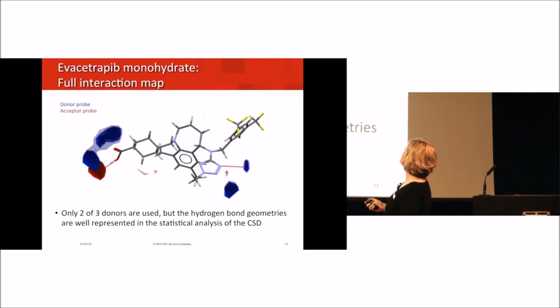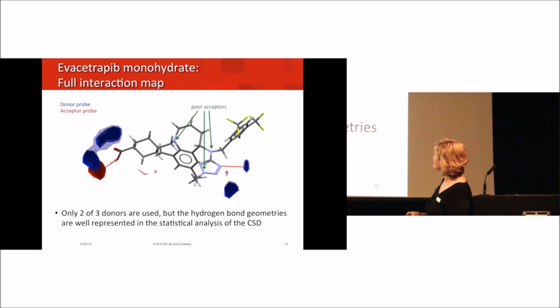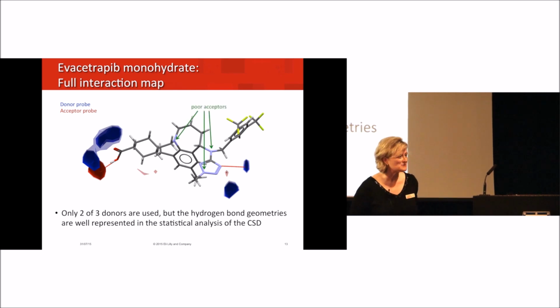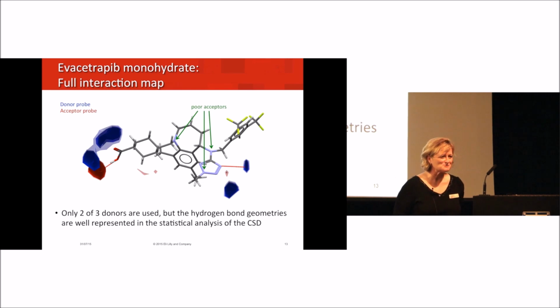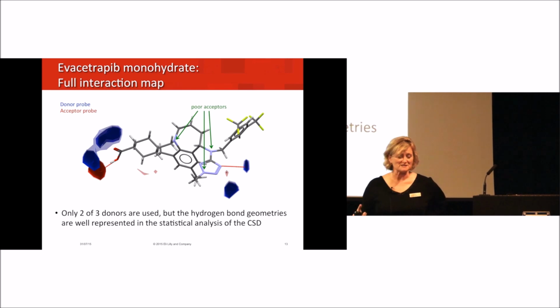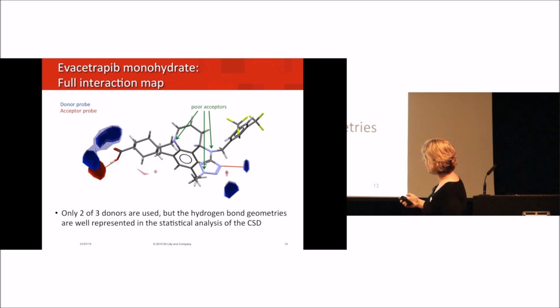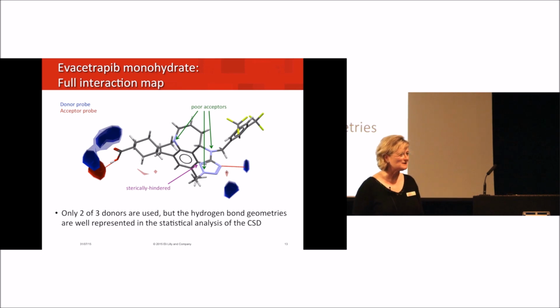And if you look at the fingerprint, this was interesting to us. This molecule is overloaded with hydrogen bond acceptors, or so I thought. And what you can see is the hydrogen bonds that do form are reasonably well satisfied from a geometric standpoint. But what you also see here is that many of the nitrogens the Cambridge Structural Database doesn't see as being good acceptors. So the imbalance of donors and acceptors was not as high as what I thought it might be. Moreover, one of the other good acceptors appears to be sterically hindered based on the molecular conformation of the molecule.